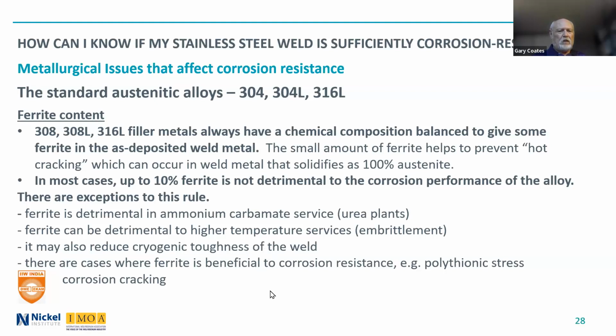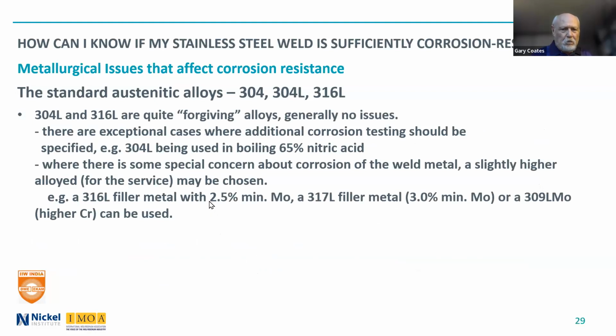And one should remember there are cases where ferrite is beneficial to corrosion resistance, and the main one that I run across is polythionic stress corrosion cracking, where ferrite will help to prevent that stress corrosion cracking from occurring, whereas the parent material that has 99% plus austenite in it will crack. So 304L, 316L, I call them forgiving alloys. So generally there's no issue. We mentioned perhaps with some cases like boiling 65% nitric acid, there is a problem. And the problem is more with the parent material than the weld material, but you usually test a weld because